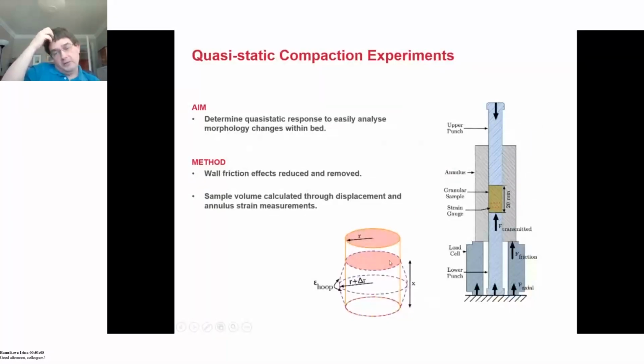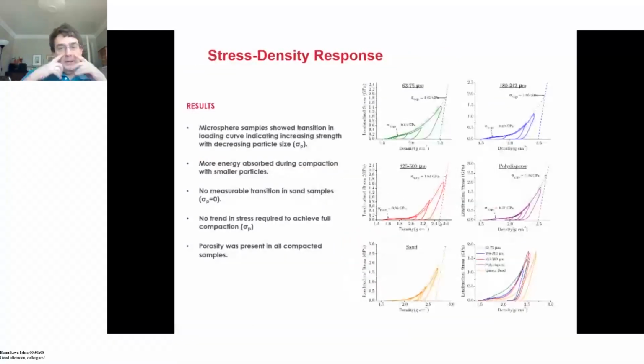So we can measure compaction. We can also include lateral expansion as well as lateral friction. What you do find doing these kinds of experiments is that up to 40% of the load that you're applying does not particularly go into the sand. A good 40% of that load will actually go into the walls of the container. So this makes a significant difference to the analysis of the results.